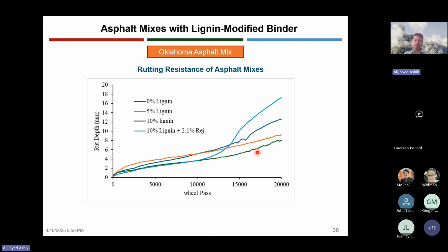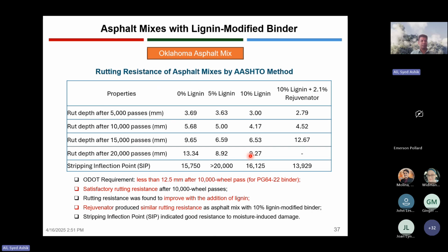So let's look at the results. We use this data to analyze different rutting resistance parameters. The ODOT requirement for good rutting resistance is less than 12.5 millimeter, or less than half an inch, after 10,000 wheel passes if the asphalt binder is PG 64-22. If we look at the rut depth at 10,000 passes, all of the mixes showed very good results. But at the same time, if we look closely, with the increase in lignin modification, the rut depth goes down. For 5%, it was 5 millimeter. For 10%, it was 4.17 millimeter. And we have seen almost the same thing for 15,000 and 20,000 wheel passes as well. So we can expect a significant rutting resistance benefit from lignin modification of our asphalt mix.